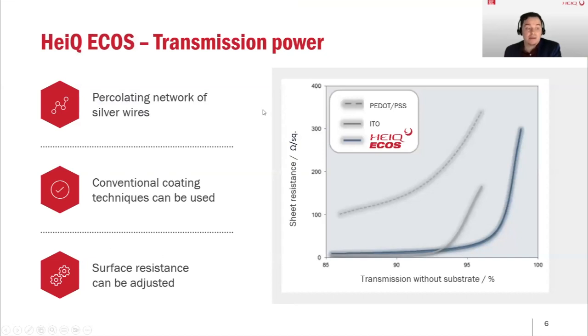And the main parameters that characterize such transparent and conductive surfaces are, on the one hand, the sheet resistance or the conductivity, and on the other hand, the transmission or the transparency. And the blue curve here is our HeiQ ECOS. And what is demonstrated here is that we can cover a huge range of sheet resistances with HeiQ ECOS, simply depending on the amount of silver wires that is deposited on a surface. And this is a very important point because depending on the target application, we need different sheet resistances. And still, from 5 to several hundred ohms per square, we have very good transparency and transmission values.